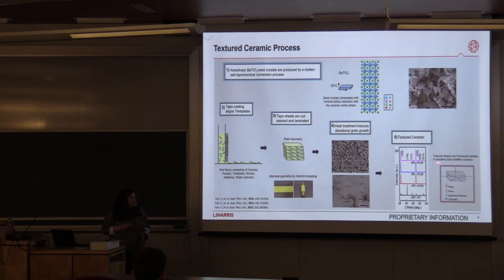And really, the best way to track this is powder X-ray diffraction. Since we're looking at something that is preferred orientation, when you look at the X-ray, this would be random, so you get a random distribution of your X-ray reflections. And then here is something where they're looking at different amounts of seeds, but what you can see is this is a textured one, and right away, once it's textured, the orientations that were there before from something that's random have disappeared, and you're now looking at all one orientation. And then this is just an example of a structure here. Once it's been heated, we electrode it, we pole it, we do everything the same as a typical ceramic, that Angie talked about earlier.